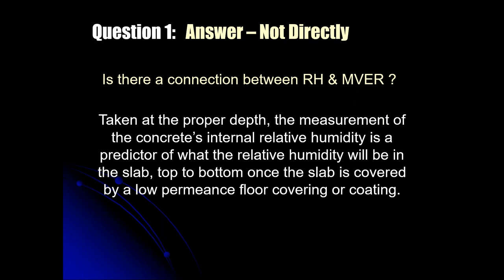And when you take the measurement at the prescribed depth, and that would be for a concrete slab on the ground or on metal deck that is only free to lose moisture from the top, the depth would be 40% of the slab thickness. So if the slab was 5 inches thick, 40% of the slab thickness is 2 inches. So by taking a measurement at 2 inches into the slab, whatever number you get at that depth is the predictor of what the slab will be top to bottom once it's covered.